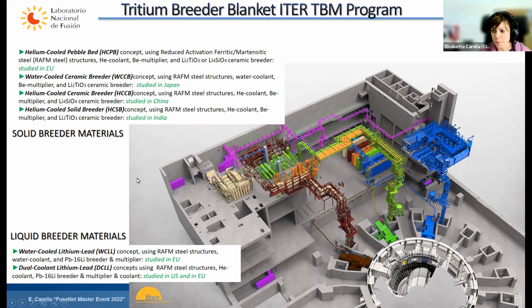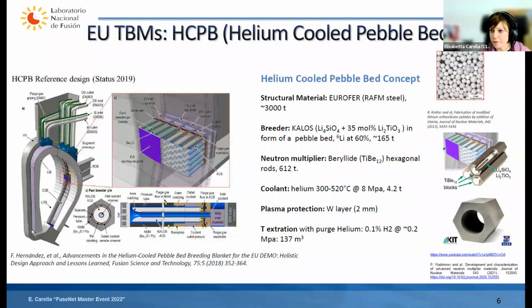Of all the TBMs proposed by Europe, speaking of HCPB, we have the neutron multiplier in hexagonal shape containing the breeder ceramics. The coolant is helium at a really high pressure. The first wall, the plasma protection, is a layer of tungsten. And the tritium extraction will occur with helium purge gas with a small content of hydrogen that can catch tritium produced inside the lithium ceramics.